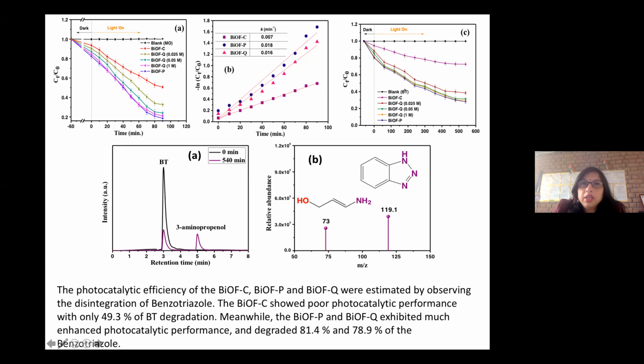And then we did the kinetic study, and you can see this is the chemical one, rate constant 0.007, but in the plant extract and quercetin the rate constant was almost similar, 0.018 and 0.016. Obviously the plant extract was a little bit more. So other constituents are also responsible, but the main responsible constituent we found was quercetin. So the degradation was seen in the BiOF process. Actually, BiOF has a higher band gap, so if we compare it with other bismuth oxyhalides, it's not giving good results. But we found that yes, the main constituent quercetin is working.